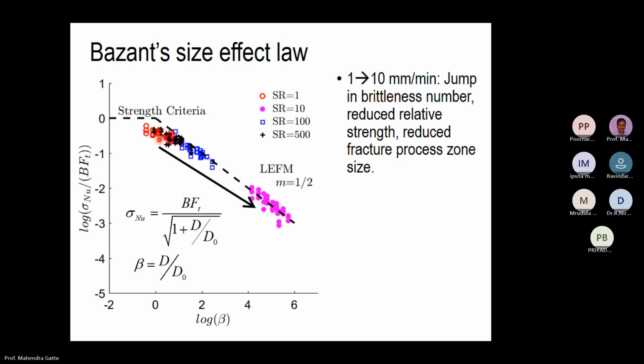And then at loading rate 10, the data is moved here. The experimental data is close to the LEFM. So we are seeing a sudden reduction in the fracture process zone size. Okay, initially, the fracture process zone size is nearly throughout the structure, and then suddenly there is a drop. So that's why we have a LEFM criteria. So all the fracture process is taking place at a point. So this is the LEFM criteria.